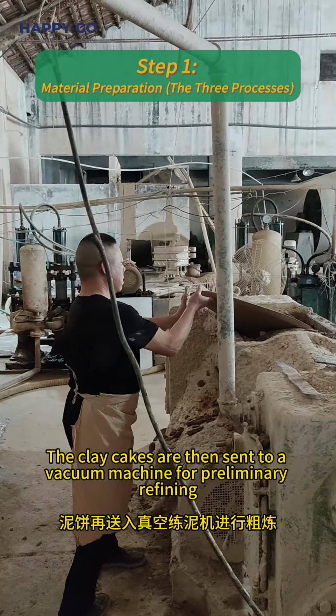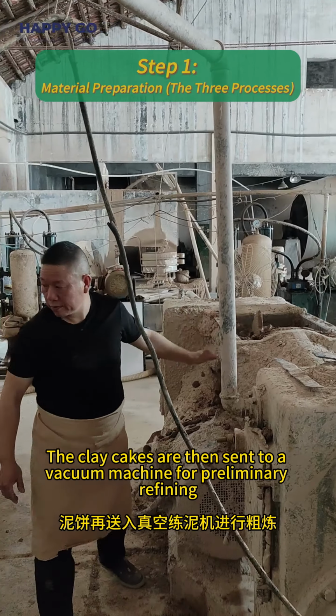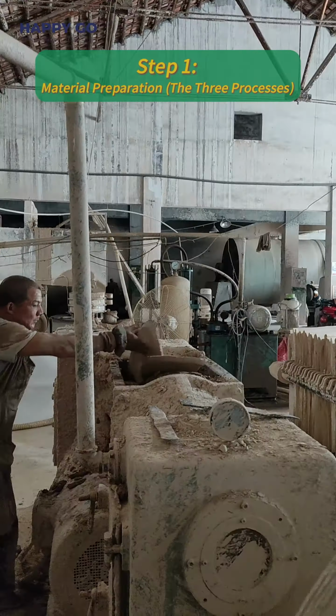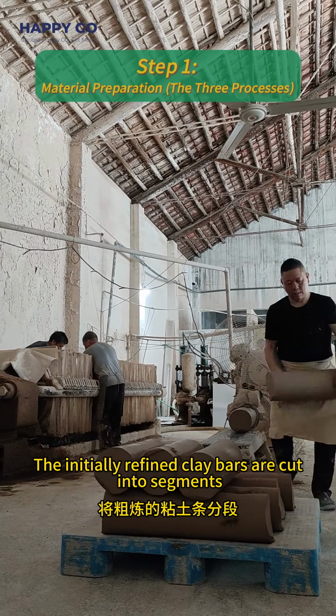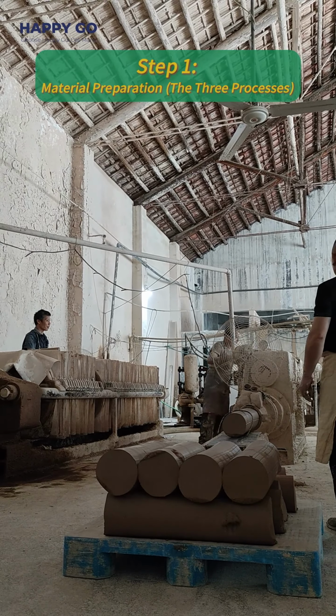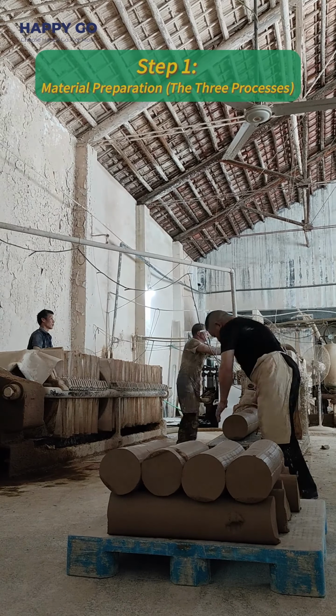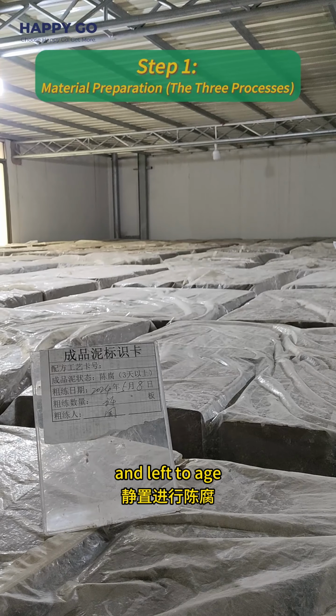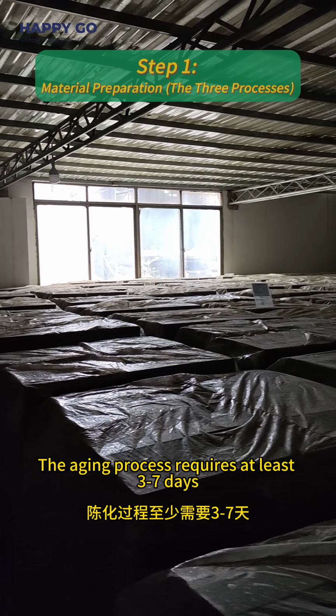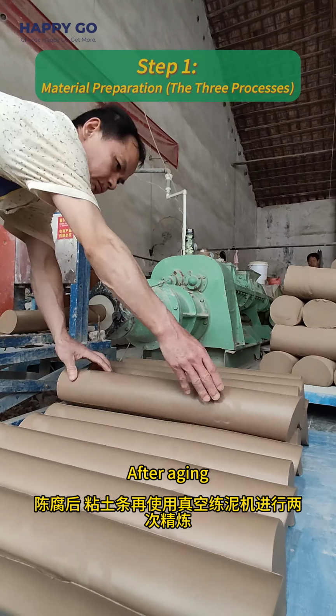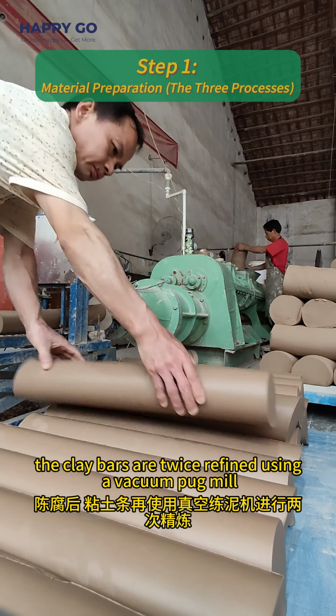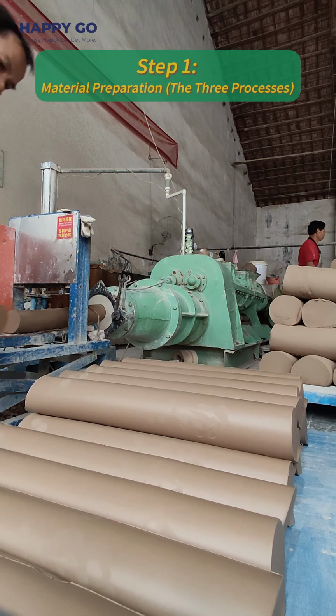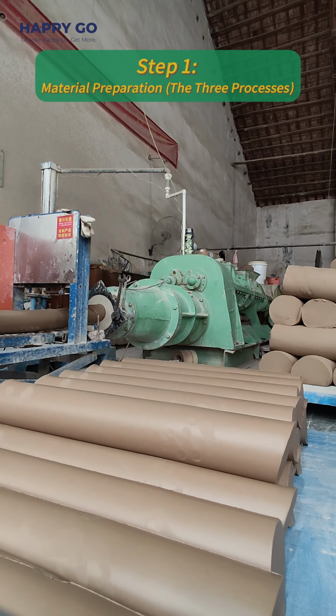The clay cakes are then sent to a vacuum machine for preliminary refining. The initially refined clay bars are cut into segments and left to age. The aging process requires at least 3 to 7 days. After aging, the clay bars are twice refined using a vacuum pug mill, and then they are ready for use.